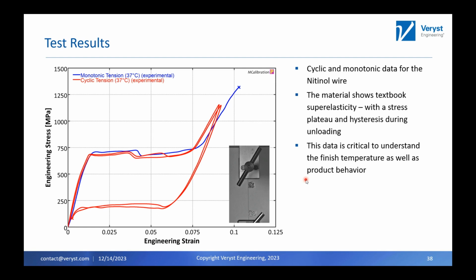So this particular wire was a nitinol test wire. If you're not familiar, nitinol is a shape memory alloy that has a lot of interesting properties that are useful for medical devices. So it's both super elastic and shape memory, so it goes to very high strains for metals. And it has this interesting behavior where you've got these stress plateaus. So you load it up, you hit the first yield stress, and then the yield stays the same, and then you get stiffening. And what's happening there is you're getting a phase transformation in the material itself.